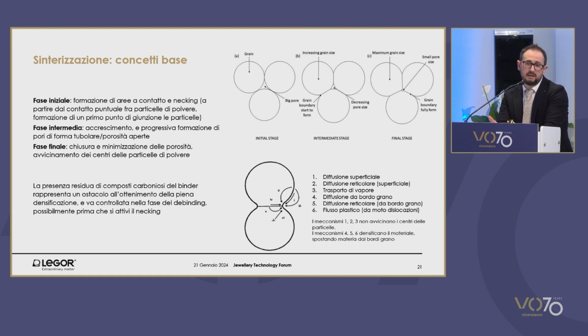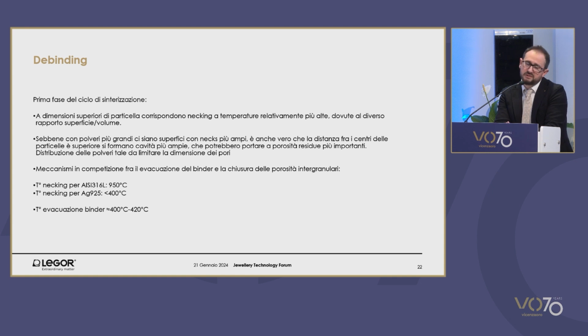So there are mechanisms of surface diffusion that allow us to obtain a meniscus which spreads then in the spaces in the powder, and then as the temperature is further increased, there are some mechanisms in the powder particle that allow for the approximation of the centers of the powder grains so that densification can occur, with the final target of achieving a residual porosity equal to 0 or very, very close to it. Very low. That is less than 0.5. For aesthetic purposes, 0.4, 0.3, bearing in mind the distribution of powders, because we're talking about an average value which is measured in a certain area, but of course the dimension of some pores could be different. There may not be homogeneity.